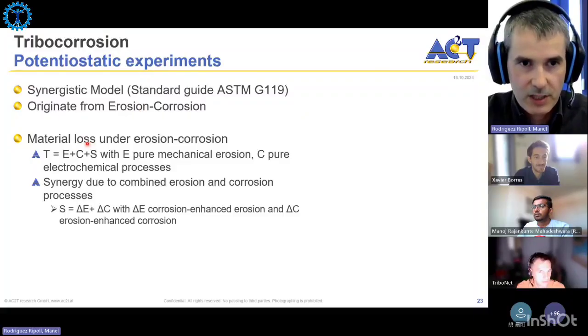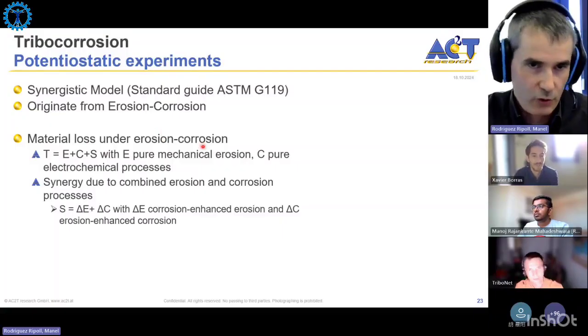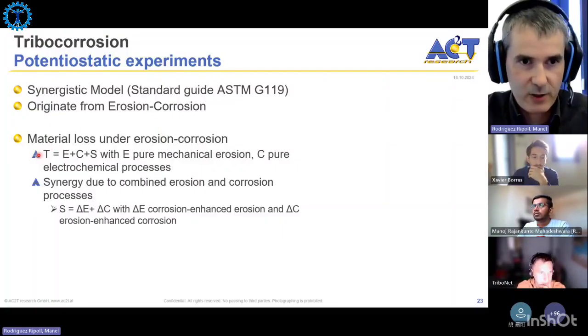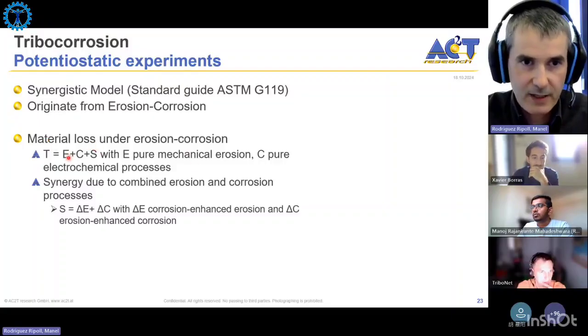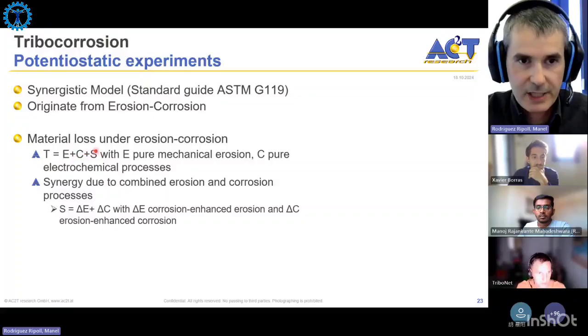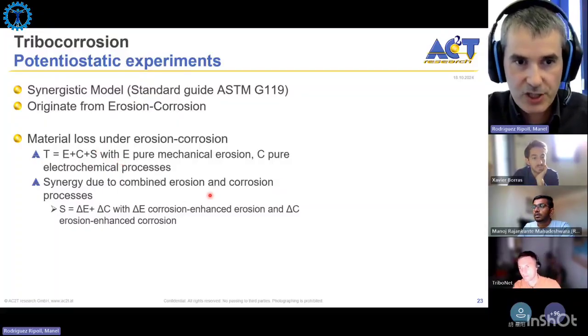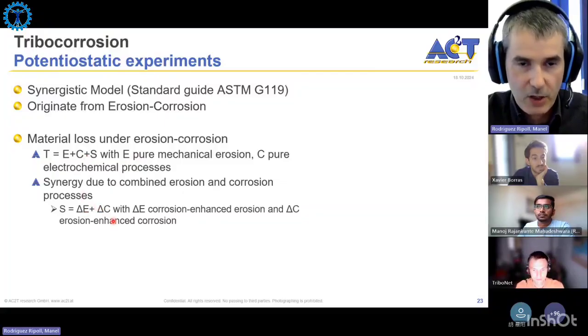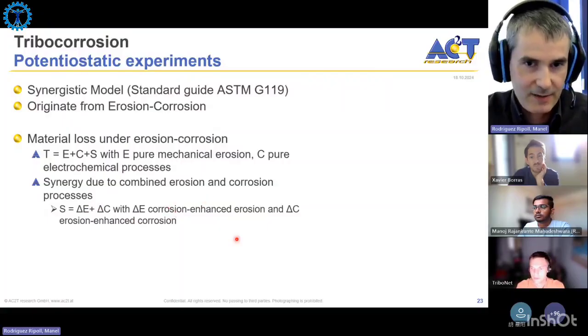So basically this model assumes that the total loss due to tribocorrosion, erosion corrosion, or whatever, so the total mechanical wear in a corrosive environment, has three contributions. So a pure mechanical wear or erosion, a pure corrosion term that is only due to electrochemical process, and a synergy term. And this synergy is the action of the combined mechanical and corrosion processes, and this synergy you can split into two additional terms. One could be the corrosion enhanced erosion or wear. So it is enhanced wear due to corrosion processes, for example, because your material gets weaker, because it gets corroded. And the erosion enhanced corrosion will be something related to wear accelerated corrosion. So the corrosion that is triggered by this mechanical damage of the passive layer.